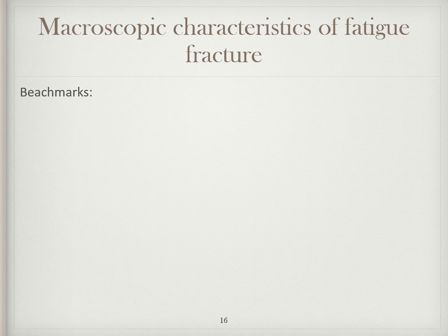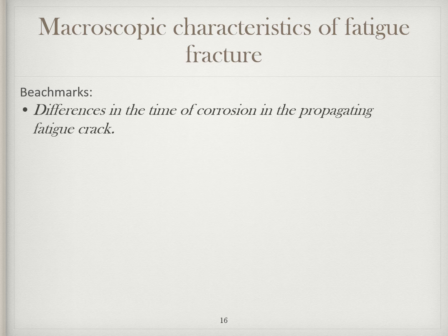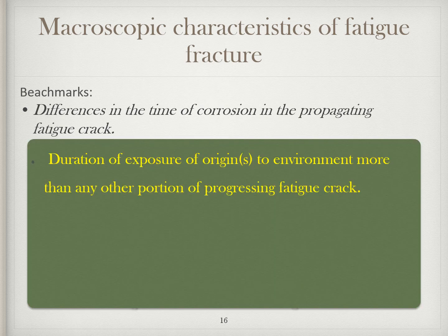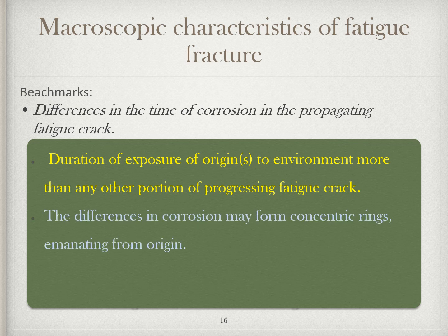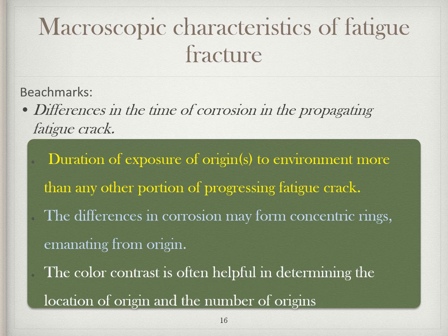The second reason behind the formation of beach marks is differences in the time of corrosion in the propagating fatigue crack. The area near the origin or origins is exposed to the environment longer than any other portion of the progressing fatigue crack. Sometimes these differences in corrosion form concentric rings or lines emanating from the origins. In some metals and environments, the corrosion products are of a different color from that of the uncorroded metal near the final rupture. This color contrast frequently is of help in determining the location and number of fatigue origins.